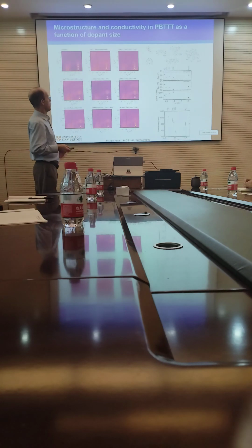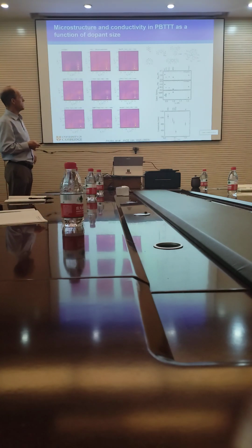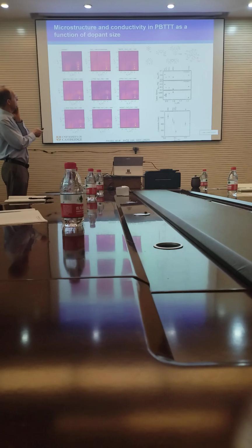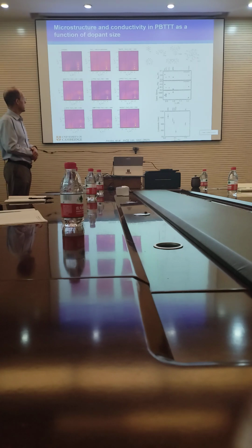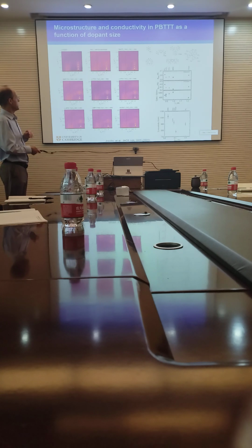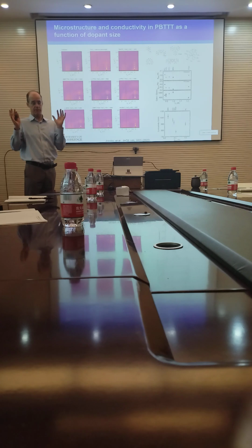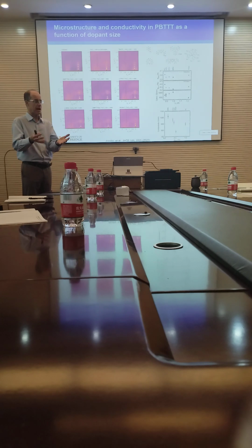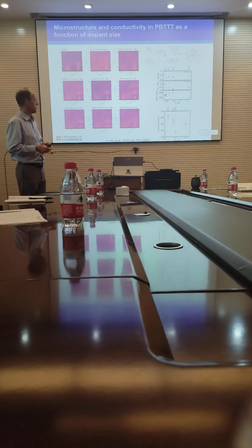And so then we looked at how this depends on the size of the anion. You can see here some GIWAXS, grazing incidence wide-angle X-ray scattering images. I don't want to discuss them in detail, but what you see essentially is that for all these ions, small to big, the polymer remains highly crystalline. You can see these clear diffractions for the lamellar packing. You can see the pi-stacking diffractions. So the polymer remains crystalline. You can put these many ions in, but the polymer remains highly ordered.